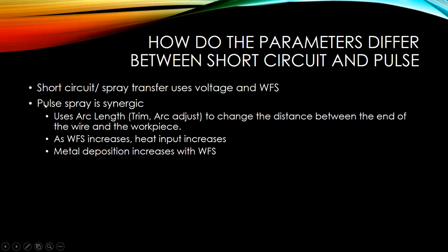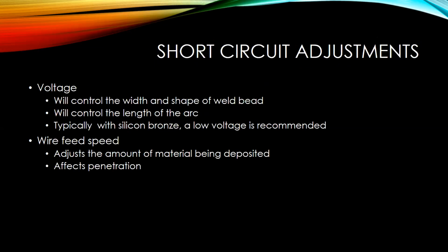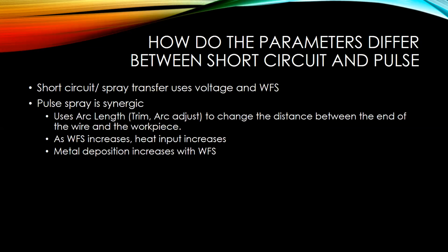If you're running pulse spray transfer, pulse is synergic. So you have a couple of adjustments. You're going to have a wire feed speed adjustment and also an arc length or trim or arc adjust. A lot of the terms are adjusting the same thing, but what that's going to do is allow you to adjust the distance between the end of your wire and your weld puddle. So as you decrease that arc length, it'll tighten that up, or if you increase it, it'll make it longer. It might affect your puddle width a little bit. If you need to narrow up the puddle, you can always tighten it up a bit. It also helps depending on the joint type that you're going to be welding up. So it allows you to adjust that.